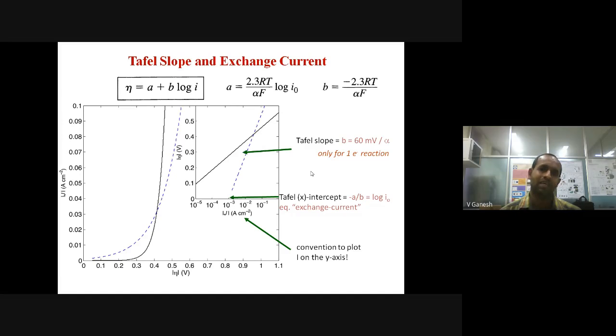But please remember, these Tafel slope values have been derived to understand the mechanism behind the hydrogen evolution reaction. Classically, they derived this Tafel slope relation. They made a Tafel measurement to understand the mechanism behind the electrochemical reaction. It does not describe catalytic activity. Please understand.